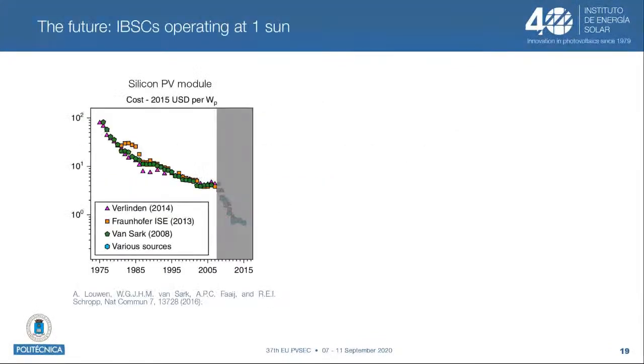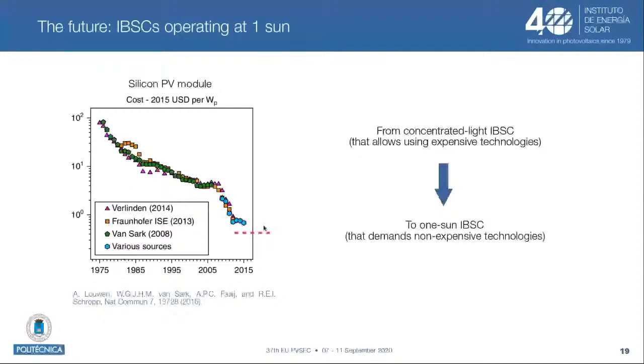Let's go back to the first graph of the price of silicon PV module. If we look now at the present, we see that the price has decreased a lot. It is around 0.3 dollars per watt peak now. And we think that in this new low price context, the ideal scenario for an intermediate band solar cell would be to achieve high efficiency in a low cost material that we can operate at 1 sun. So we propose a shift in the mindset from very high efficiency devices under concentrated light to cheap devices that can work under one sun.